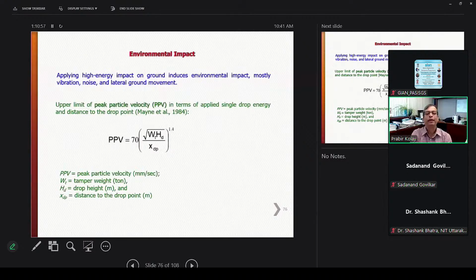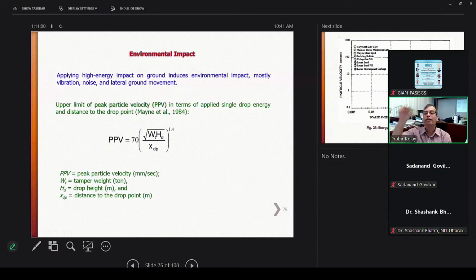So what is going to happen when you impact it? How much is the peak particle velocity? We need to check, so we need to calculate the peak particle velocity. High energy impact on the ground increases environmental impact, mostly vibration, noise, and lateral ground movement. So basically, how much the Rayleigh waves, different waves. So the upper limit of peak particle velocity, Mayne et al. 1984: peak particle velocity equals 70 times square root of (W T H D) by X d P, power 1.4. So this is tamping weight, drop height, and the distance from the drop point. So you need to calculate all these things.